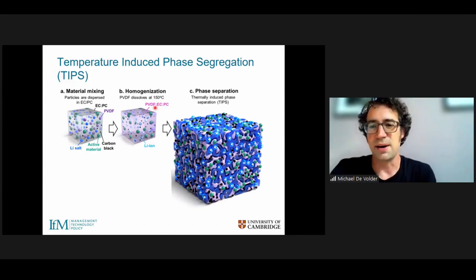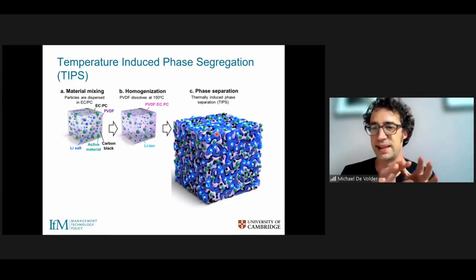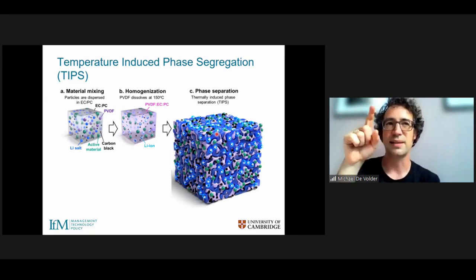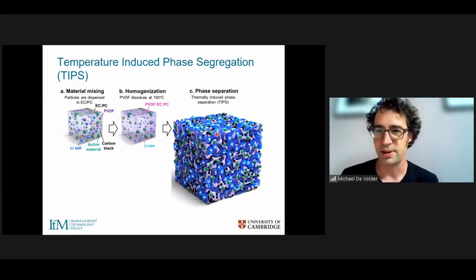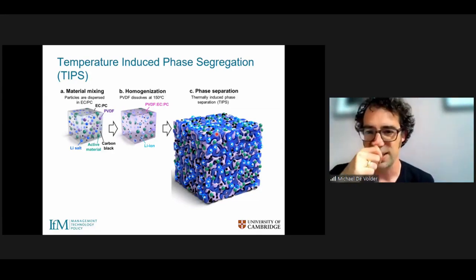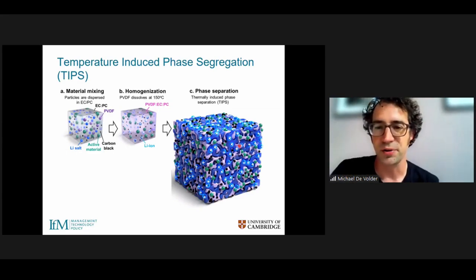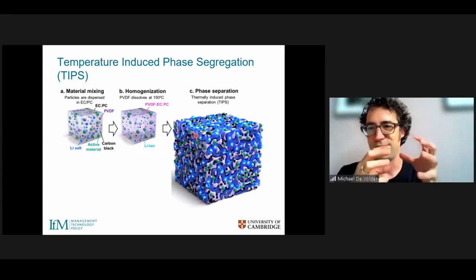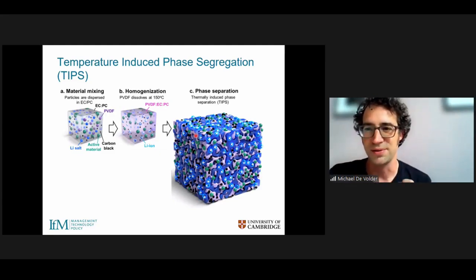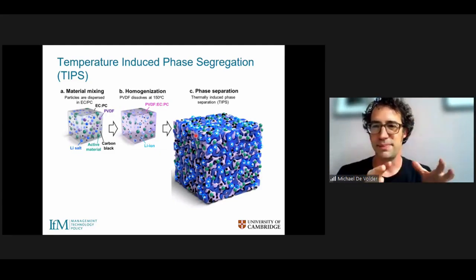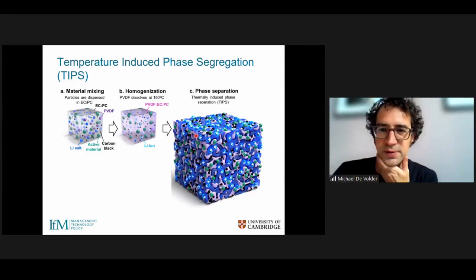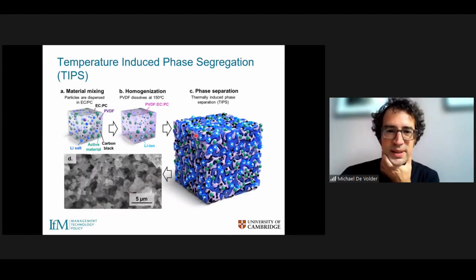And so what's interesting now is that we get two phases. One phase here depicted in blue contains the solvent and lithium salts and forms the electrolyte. So it forms a network that allows to transport lithium ions very rapidly through the thickness of the electrode. And the second phase that's formed contains all the little houses, if you want, where you can put the lithium ions in. So we are forming a nice three-dimensional bicontinuous network for storing our battery materials.